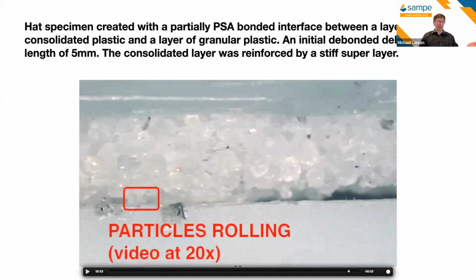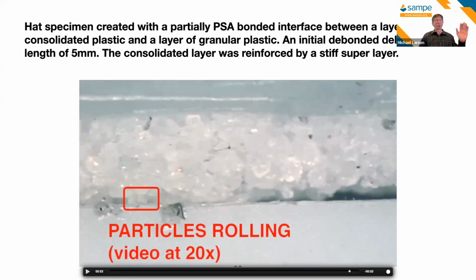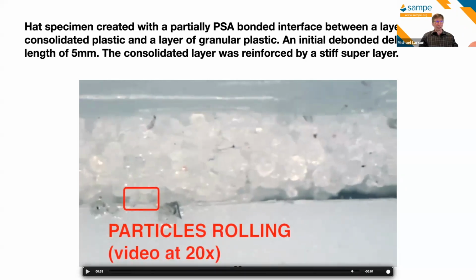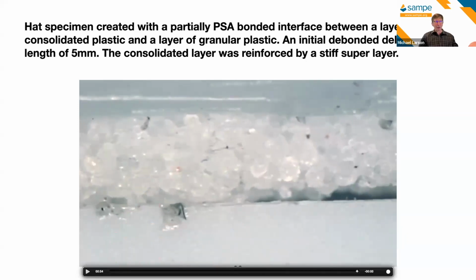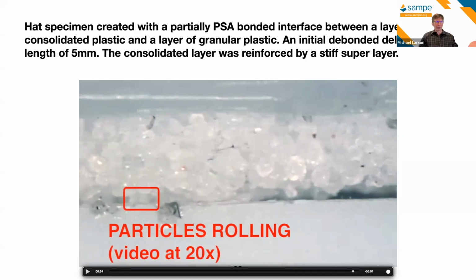So we're not particularly interested in this for things that lend themselves to a continuum model. If we tried to do that with this sort of material, I think we would miss the boat because of a much different failure mode. And even after this much deformation with particles rolling, the two parts were still hanging together with the PSA. So we just offer that as food for thought tacked on the end. And again, I think the study of granular materials and looking at ligaments holding the constituents together is important.